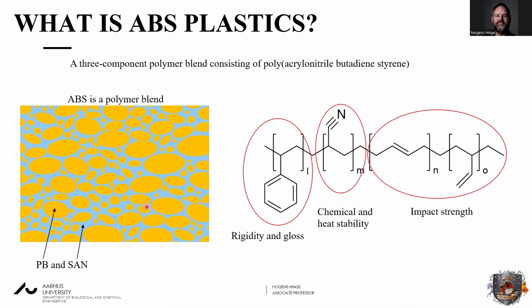Now, if we dig a bit deeper into it, then ABS is a polymer that is constituted of 3 different monomer systems, or 3 different polymers. So you have the polystyrene here, which is the part of the SAN phase, and that is taking care of gloss and rigidity of the material, but also the processability. So having the styrene phase is beneficial for these properties. If you take the acrylonitrile phase, which is also part of the blue matrix, then this is mainly giving the ABS material chemical and heat stability. So again, a very stable base to have.